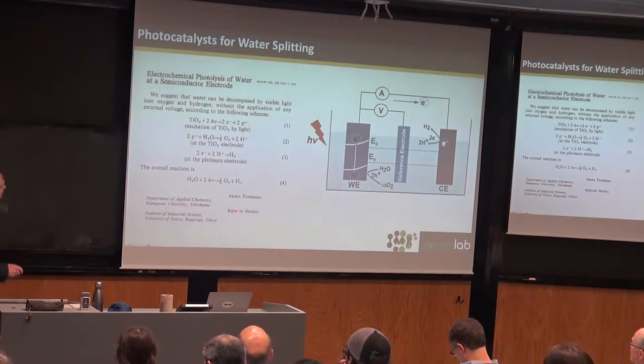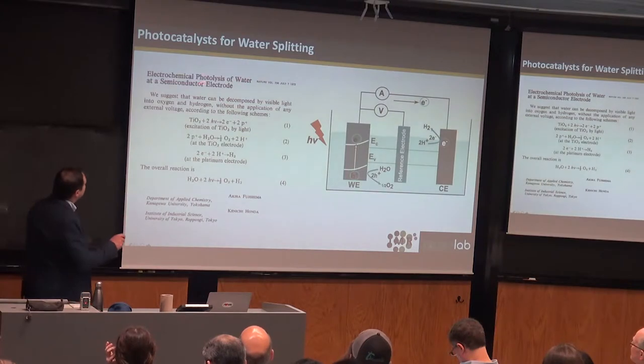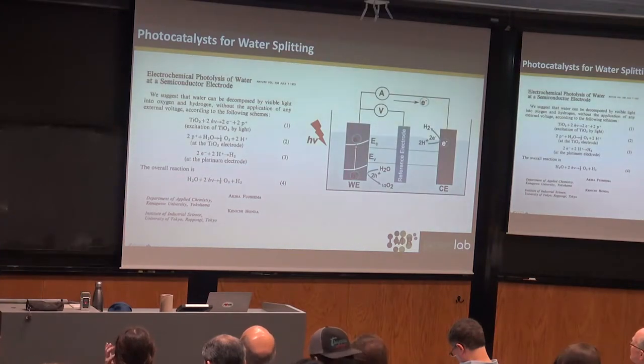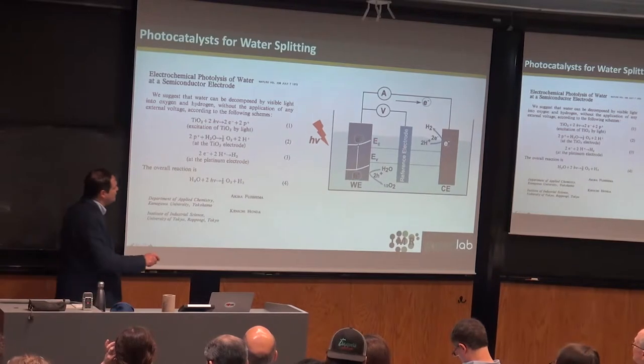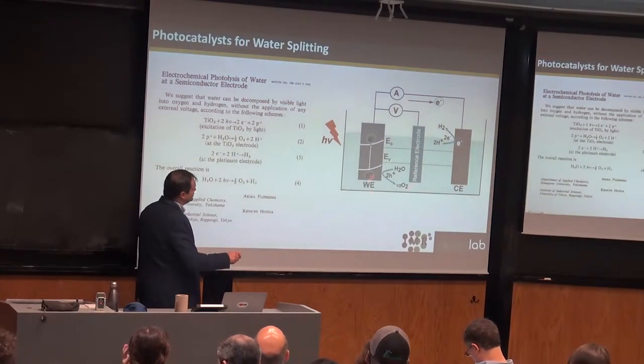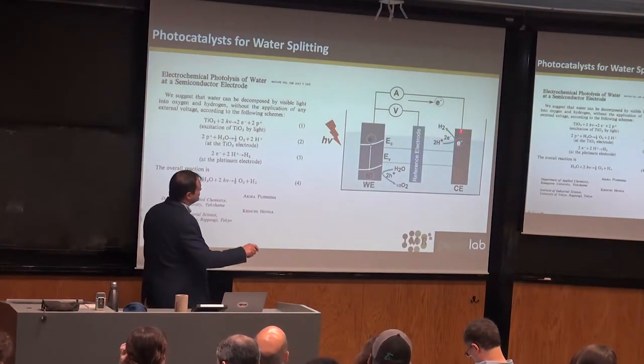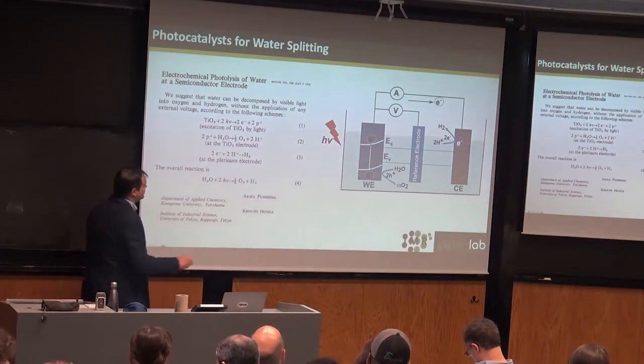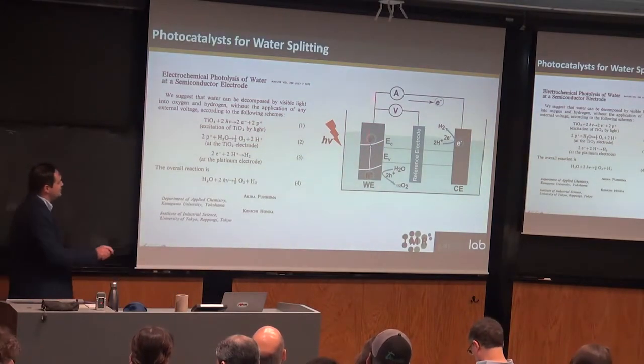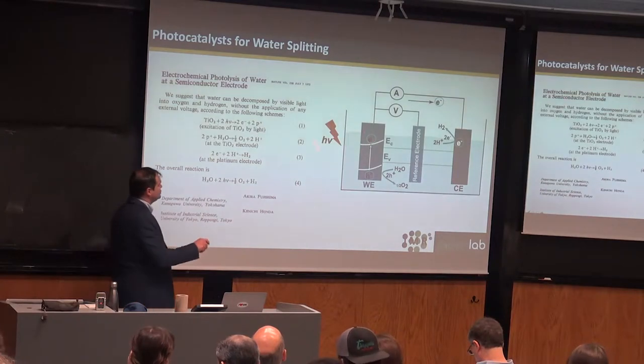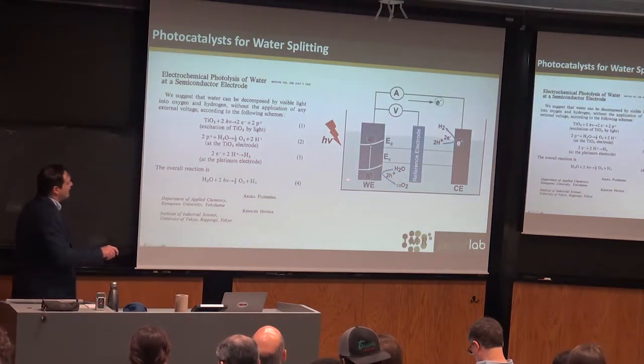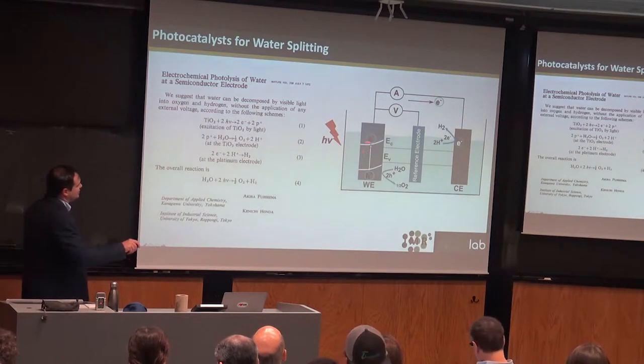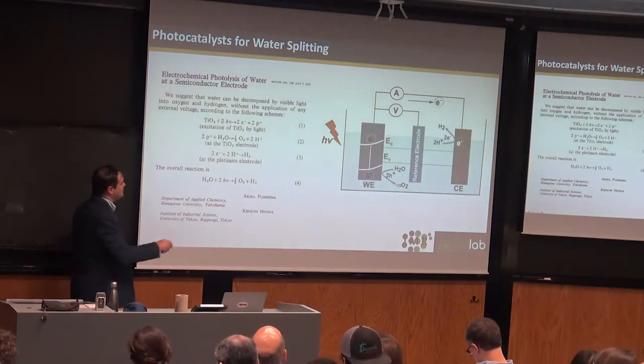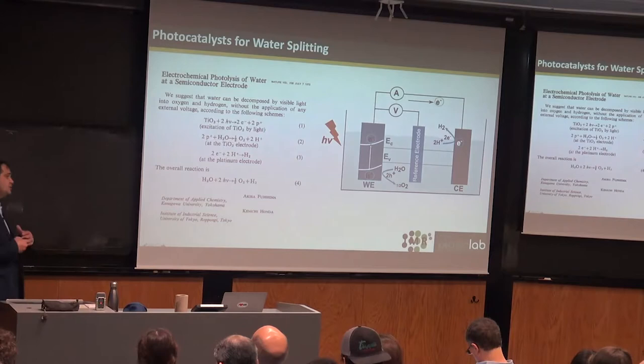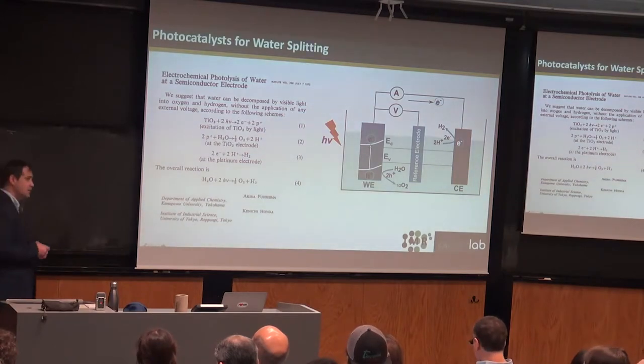And so one of the other ones was Honda and Fujishima in 1972, who came up with photolysis of water using semiconductors. And so they split the two half reactions. You have your water oxidation here and your hydrogen evolution separated by two electrodes. And the idea is that the titanium dioxide was used to both absorb light and generate the charged carriers that were then separated for your two redox reactions, and they proposed that you should be able to do this without an overpotential with visible light.